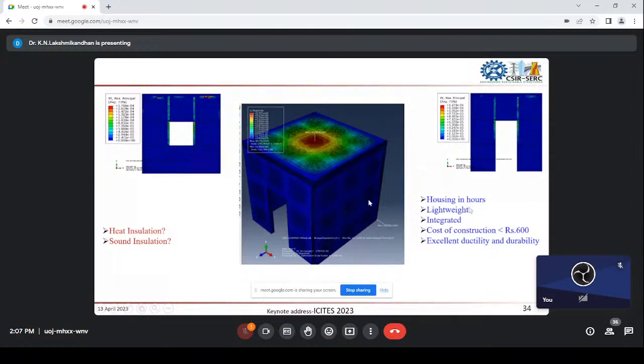These houses can be constructed in hours, within 12 or 20 hours we can construct a G+2. It is lightweight to handle, and all the components are integrated together so that the entire structure acts together during load transmission. Similarly, the construction cost drastically comes down when using ferrocement housing. It comes under less than 600 rupees per square foot, which is very low compared to what is in practice now, around 1,500 to 1,800 rupees per square foot. Regarding durability and ductility, because of the nature of the material acting together as a single material, it exhibits good ductility and good durability over time.